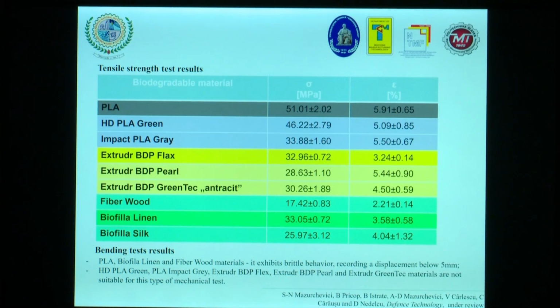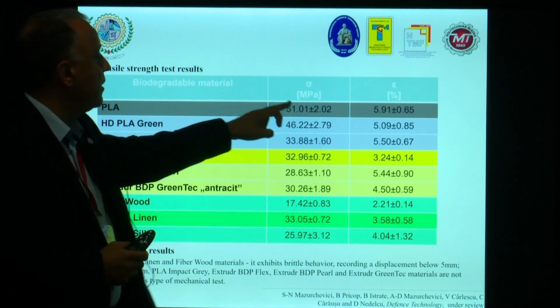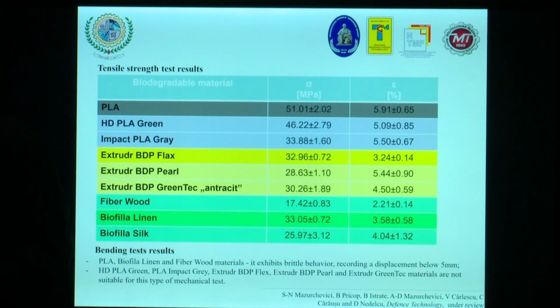You can see over there that the best results were obtained in case of PLA, I mean 51 megapascal. I saw some research in the technical literature, 46 megapascal, 48 megapascal. But it's up to the technical parameters that we used, and it's not compulsory to be, of course, the same value.